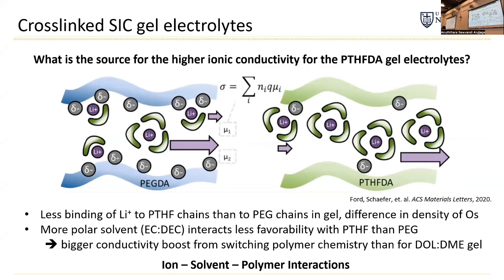We believe the difference is what the polymer morphology is inside of the gel. So essentially, if you have the poly-THF, which is more hydrophobic, in contact with this polar solvent, it's going to start to approach more of a nanostructured phase, where the polymer chains are going to come together, and then we have more channels that are totally liquid filled. So you have a lower probability of the ion going through a larger solvent channel and getting stuck on the plastic, essentially, when it's moving.